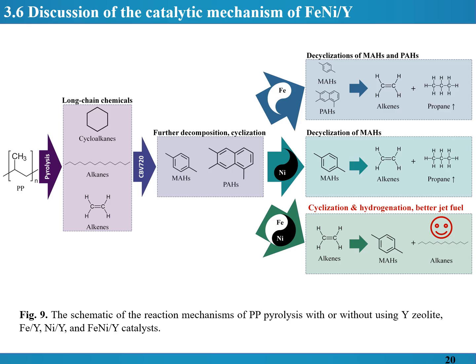polyaromatic hydrocarbons. With the doping of iron or nickel, the mass yield of monoaromatic hydrocarbons and polyaromatic hydrocarbons decreased. In contrast, the mass yield of alkene increased significantly. When both iron and nickel were introduced, the mass yield of alkene was the lowest. The iron-nickel bimetallic catalyst exhibited the opposite effect compared to the individual use of iron or nickel alone.